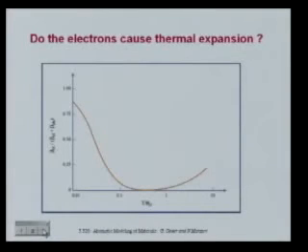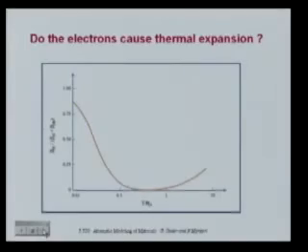Now, why is it so important here? Anybody know? It's actually because the phonon one is really small. Remember, this is the ratio of the two. When you're at a really low temperature, the thermal expansion is very small in general. And the reason is you're essentially harmonic in your phonon degrees of freedom, so you have almost no thermal expansion. If you have fully harmonic vibrations, then the entropy does not change with volume. Because if you are in a quadratic, your curvature is the same everywhere. So your frequency is the same everywhere. So your phonon frequency is the same. So your entropy is the same everywhere. So at very low temperature, you have almost no phonon thermal expansion.